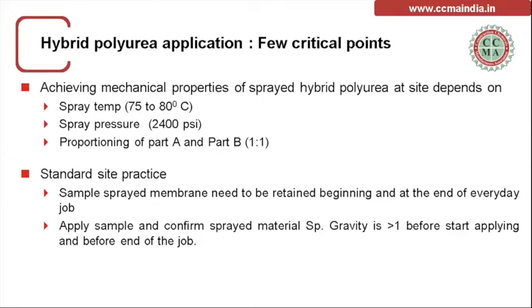So how do we make sure at the site? Every day, we spray a small area in the beginning, about a square foot. If we achieve a specific gravity of more than 1, the sprayed membrane will sink in the tumbler. If the membrane has not achieved a specific gravity greater than 1, then it starts floating on the water. That is a very indicative test. It's a very powerful test we have to do every day at site. And if it floats, then go back and adjust the equipment to achieve the required properties. So this needs to be done every day at the site before applying and at the end of the job.